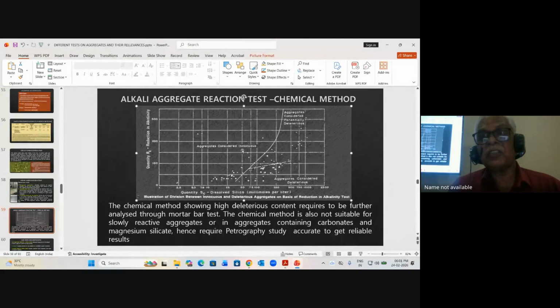So there is an innocuous zone and noxious zone. Consider the innocuous zone - the aggregate has to fall in the innocuous zone when you do the chemical test. But there is a limitation with this test also, because it will not be effective for aggregate containing carbonates and magnesium silicate. Hence, whenever you do this test, petrographic study is also very important - so this chemical test along with petrographic study is required.